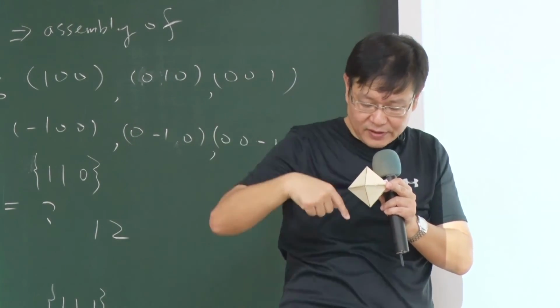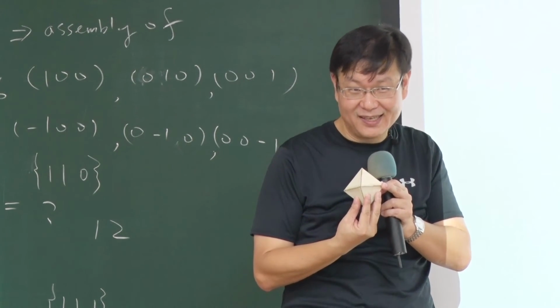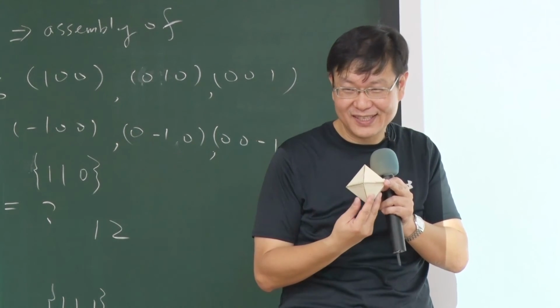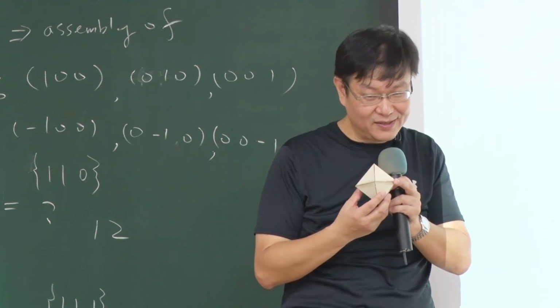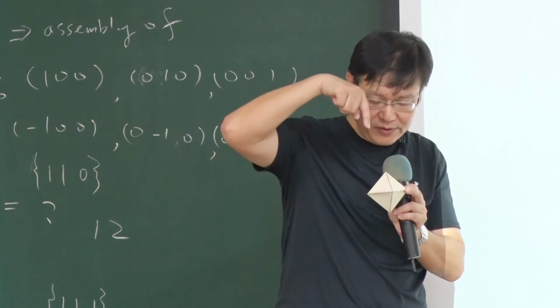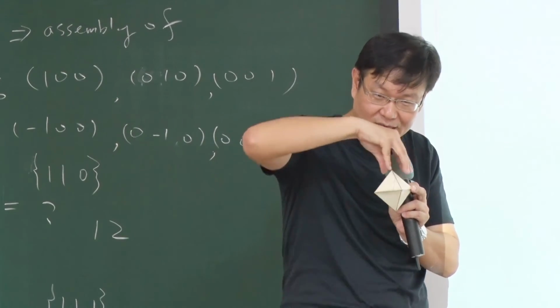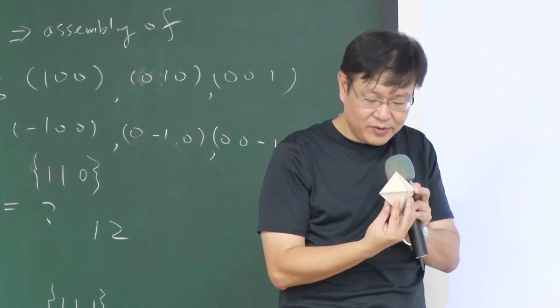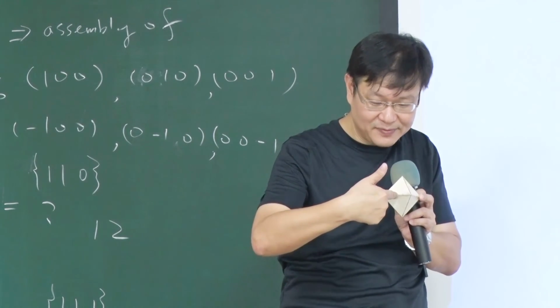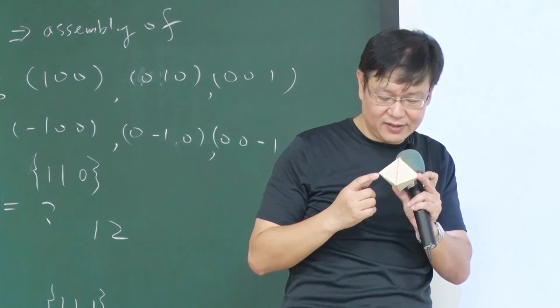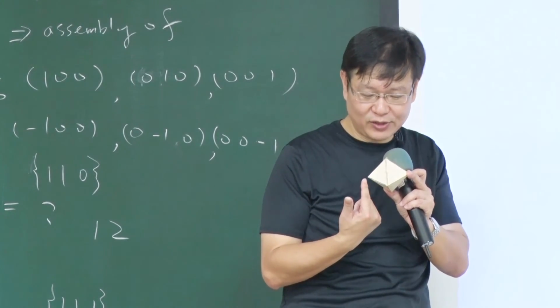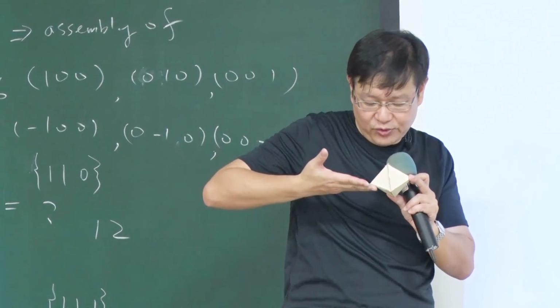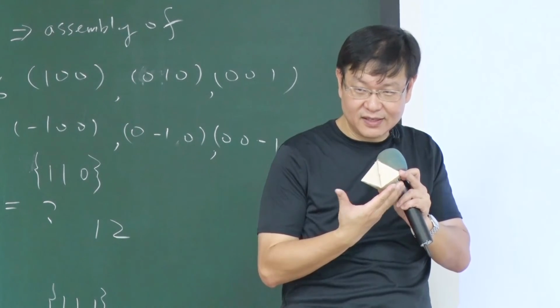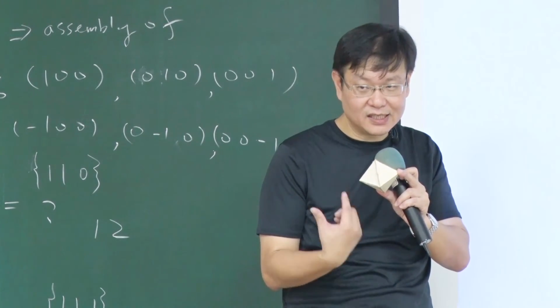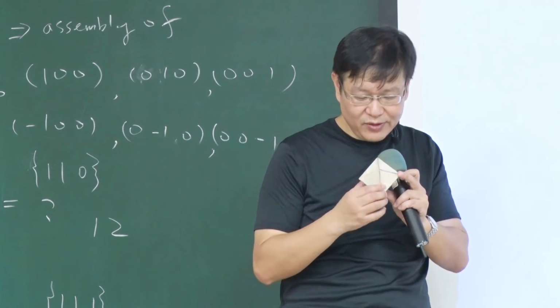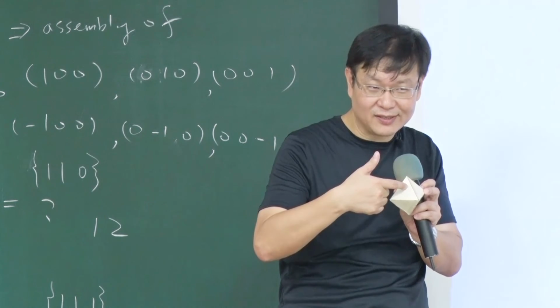If you look from the top to the bottom, you see the pyramid structure, right? That's the most familiar structure you will have from all the textbooks. But the other two directions are not that familiar. If you look from the 100 direction down, you see the pyramid structure, either on the top or the bottom. When you look from the 110 direction down, what do you see? You see the 6-face structure. The 6-face structure has 4 vertical planes and 2 inclined planes. It's like the bottom of a boat, right? Now, if we look through the 111 direction, what do you see?